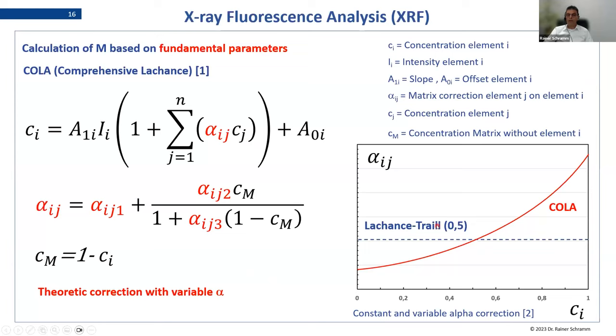Yeah. And if I compare this to the other model with the constant alpha, you see that both models will come together at the typical concentration I put for the constant alpha. This would be here at 50%. And only there I get the same result. While if I go far, far away from it, then of course the COLA model will fit much better than this constant alpha model. Yeah. But both together have the idea that you use the fundamental parameter approach to calculate your alpha coefficients. And in this way, you don't need standard materials to calculate a matrix correction. You still need standards to get the slope and the blank value.